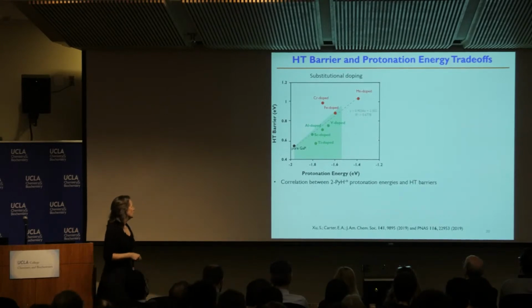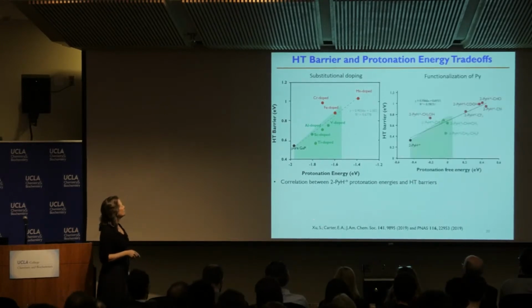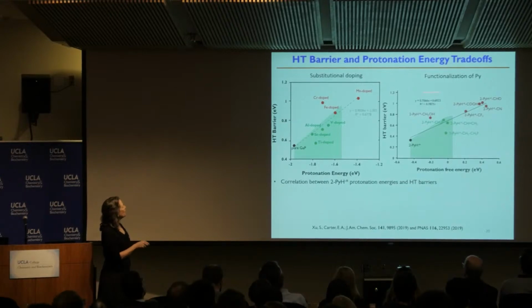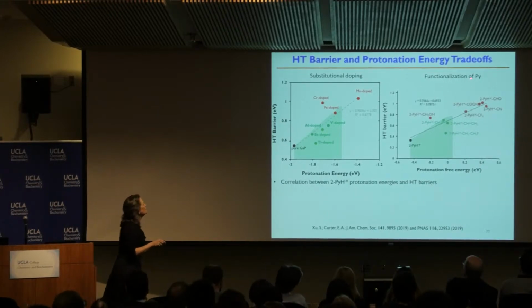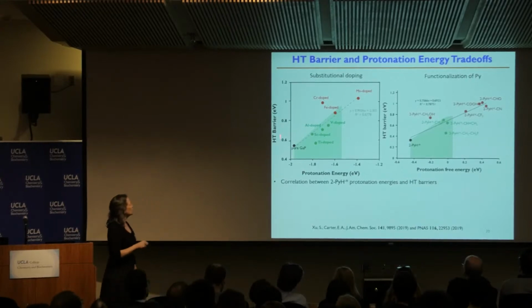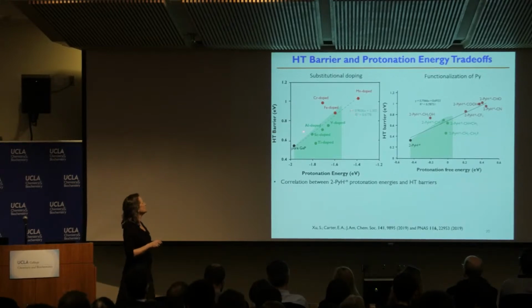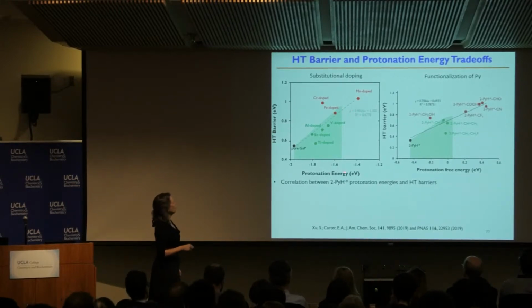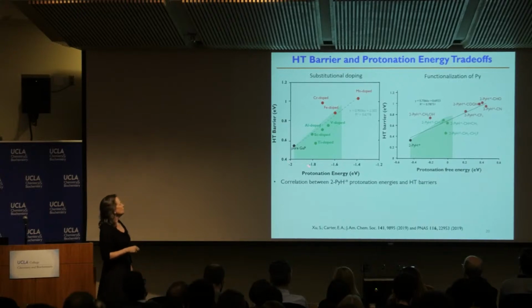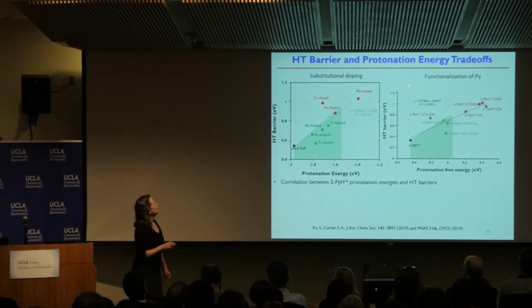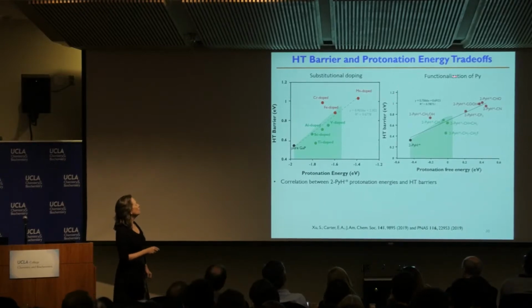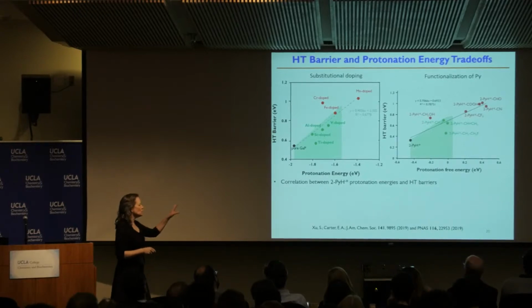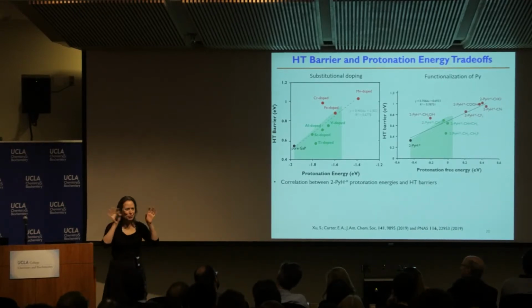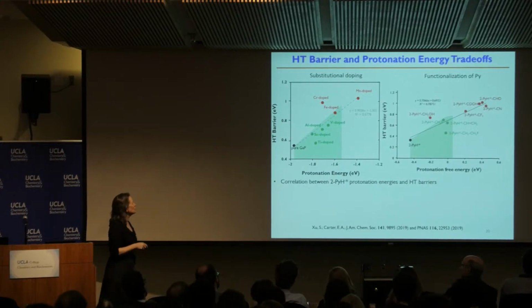And that's what he did in our most recent work that just appeared a few months ago, and that is to look at both substitutional doping and functionalization of pyridine, and to compare the hydride transfer barrier. Here, this is doping at the gallium site where the pyridine is attached to the protonation energy. We're trying to get this protonation energy to be less exoergic. And here we have an example then for functionalization of pyridine, a bunch of different substituents. Haven't told you, we looked at meta, para, ortho, we looked at everything, okay? This is just showing you the best results.